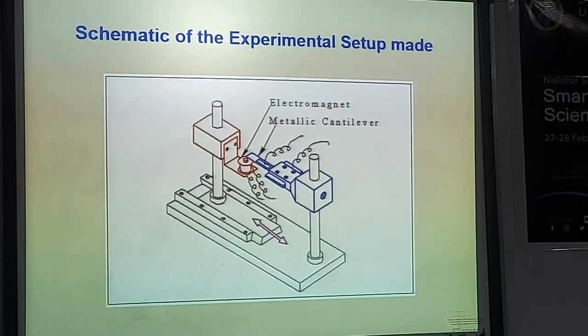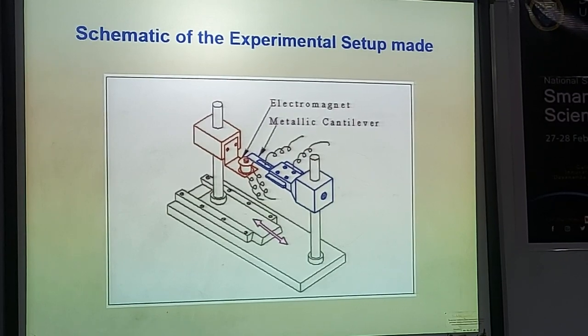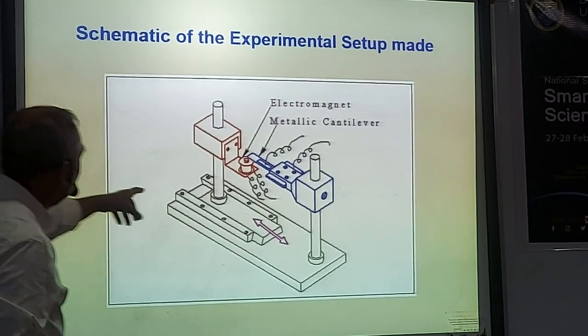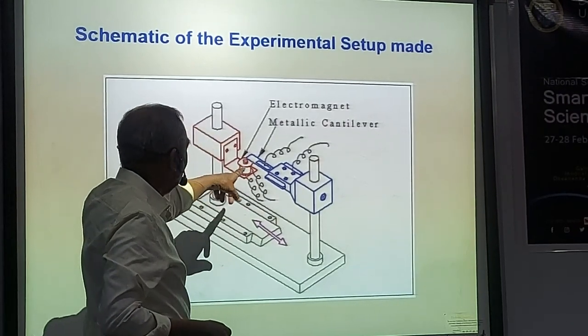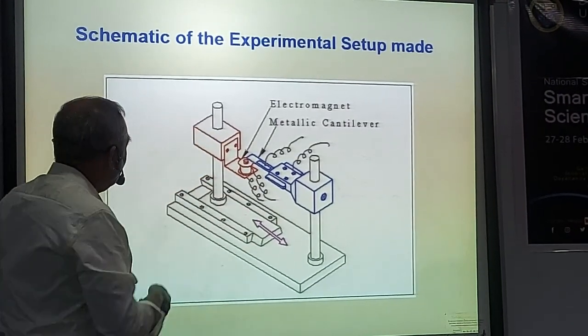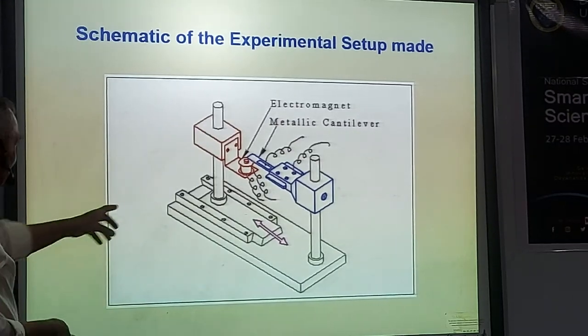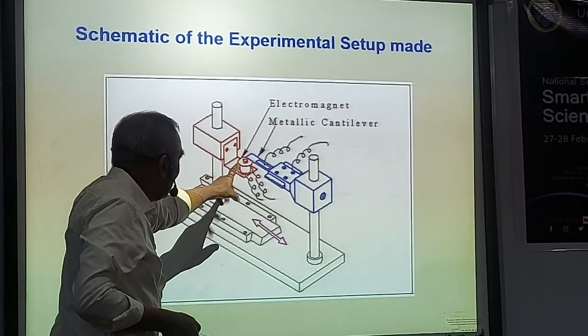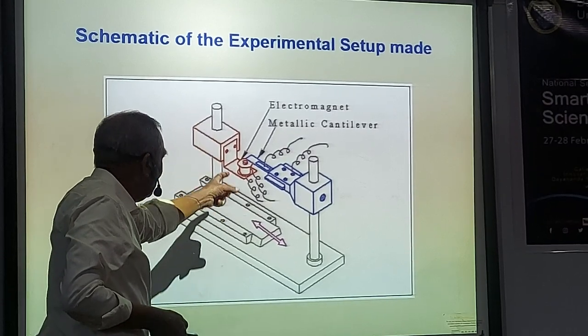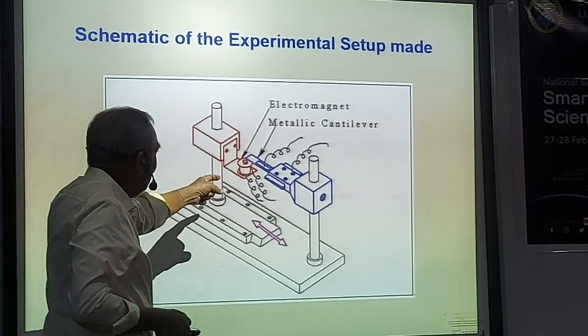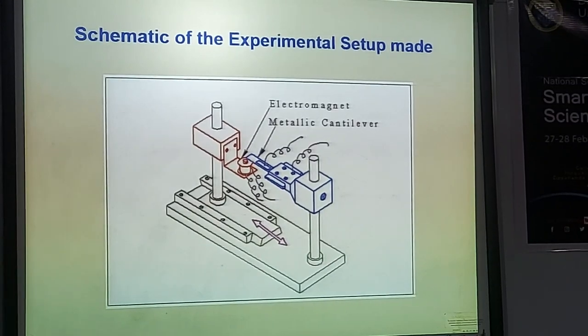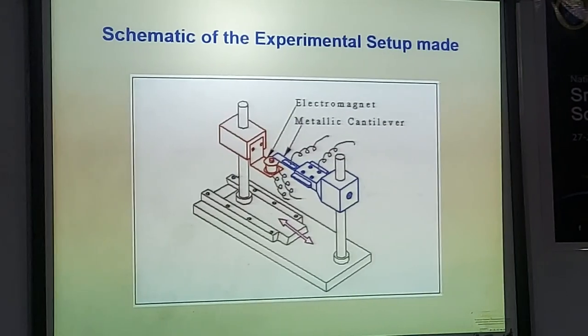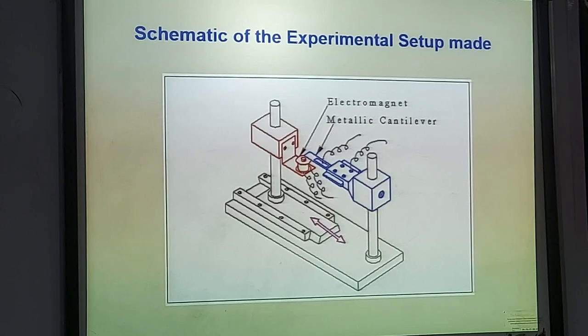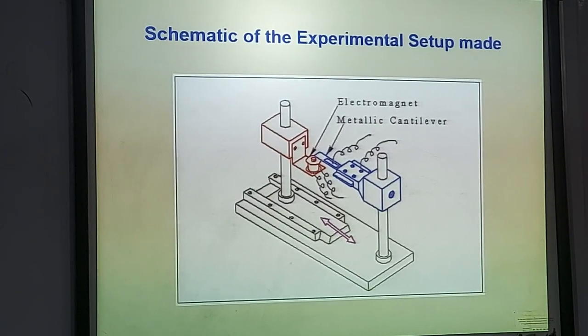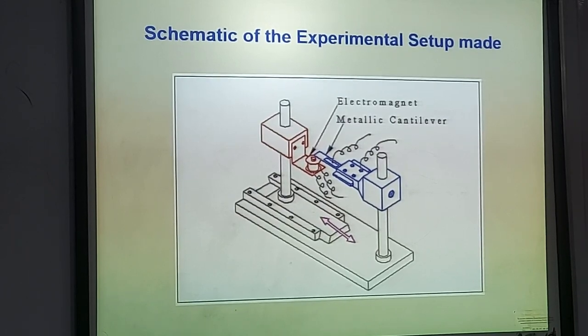So this is a schematic of the arrangement that we use. What is shown here is a strip onto which the zinc oxide film is deposited. And this is the arrangement to deflect the cantilever beam. It will attract when it is energized. When we remove the potential, it releases, so the cantilever beam starts vibrating. If the deposited film is piezoelectric in nature, charges will develop and we get a corresponding voltage in the oscilloscope. That's what is shown here.